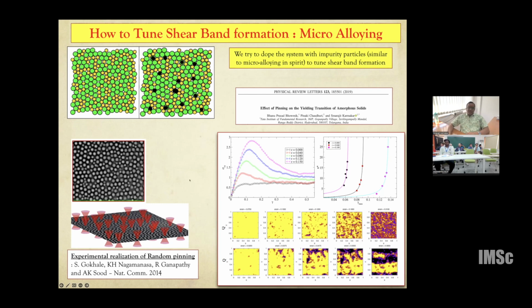This random pinning is not a very ad hoc thing, because it has also been experimentally realized in the group of Rajesh Ganapati and Ajay Sood. They were able to do laser trapping and looked at various dynamical and mechanical properties of this pinned system. So there is a very large literature which actually started from this direction.